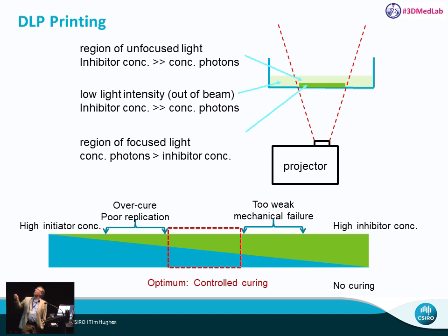But the light beam goes beyond just where we want curing to go, and you may get unwanted curing. So to stop that, we have inhibitors in the mixture to stop the unwanted polymerization. So you've got to carefully balance the levels of initiator and inhibitor. If you have too much inhibitor, you get no curing. If you have too high initiator, you get overcuring and you get poor shape replication. And there's a sweet spot somewhere in the middle where you get nice controlled curing, and that's where you want to operate.